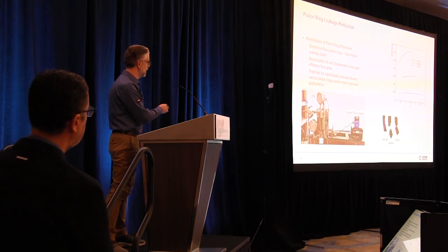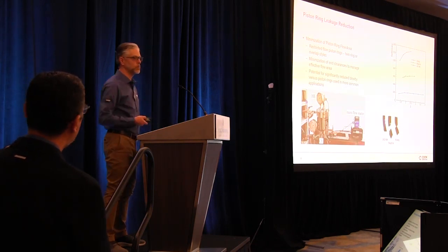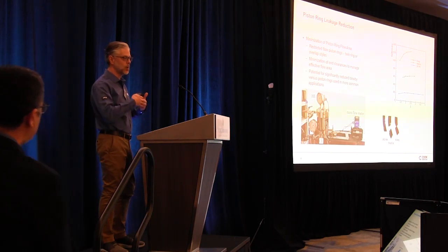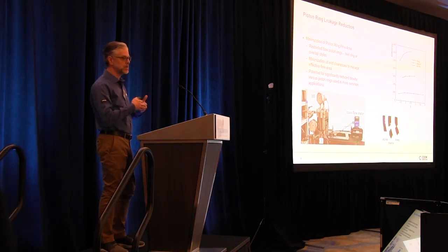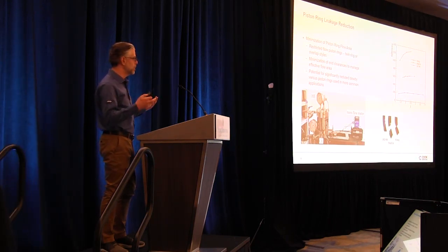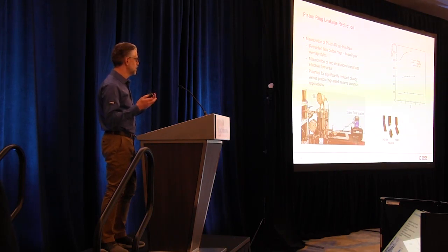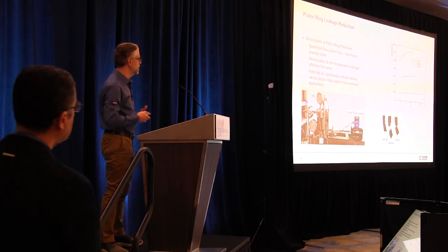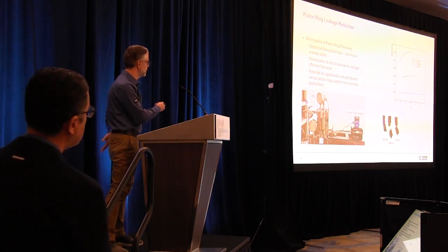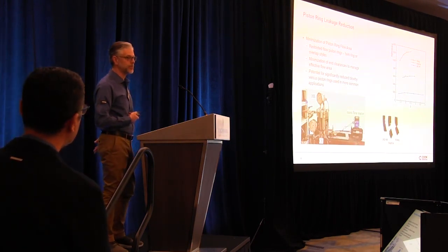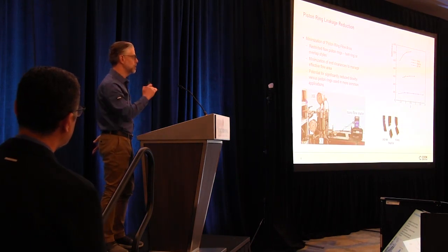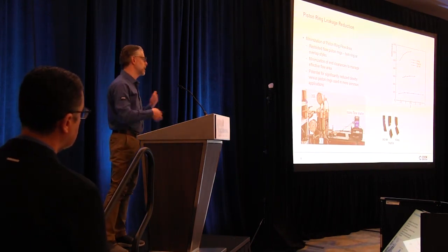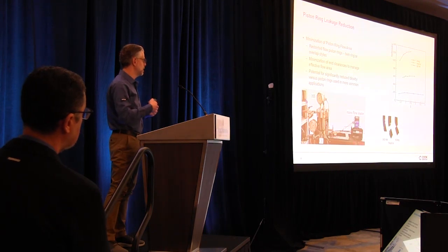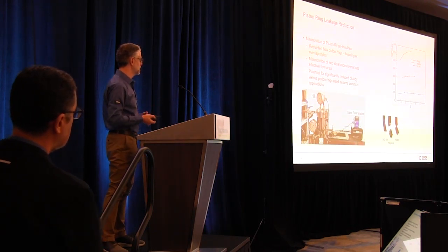So now we're looking at things like some unique twin ring designs that are more of a tight seal, positive seal, a little bit less prone to thermal expansion type issues, that can cut that down by another factor of 3. So we can really continue to reduce that leakage. So we're continuing this work as we optimize our piston ring design and selection.